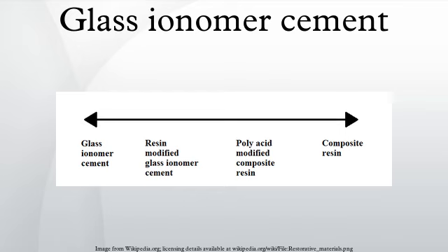For restorations placed in the permanent dentition, no difference in the failure rate of single-surface GIC and conventional amalgam restorations after 1, 2, 3, 5 and 6 years. A 61% lower failure rate of single-surface GIC restorations than that of conventional amalgam restorations after 4 years. No difference in the failure rate of multiple-surface GIC and conventional amalgam restorations after 1, 2, 3 and 4 years. An 80% lower failure rate of multiple-surface GIC restorations than that of conventional amalgam restorations after 2 years.